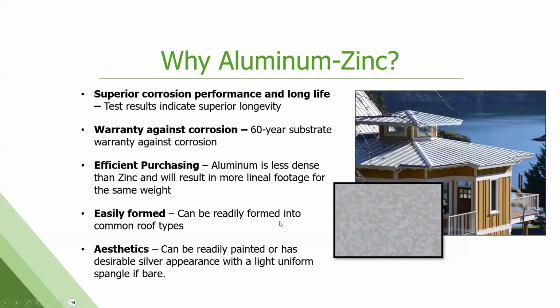So again, why do we want to use this product? Well, the superior corrosion resistance, so it's going to last way longer than anything else. You can actually get a warranty for corrosion on this product, which you cannot do on galvanized. Warranties are out there now up to 60 years on the substrate for corrosion performance. They vary from 40 to 60, 60 being the longest. Kind of depends on coating weight, whether it's painted, how close to the ocean you are, those kind of things.